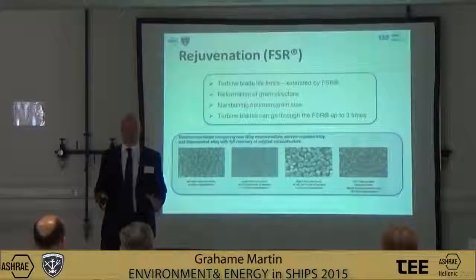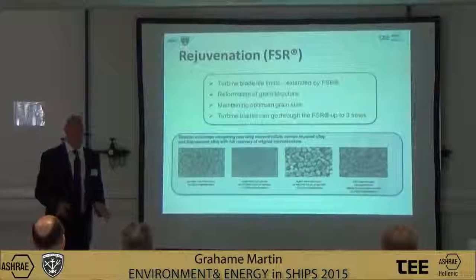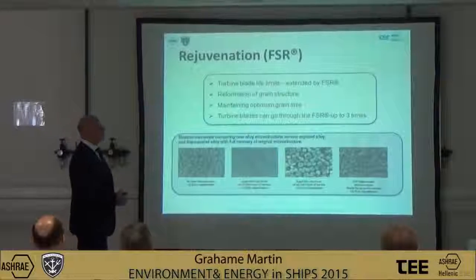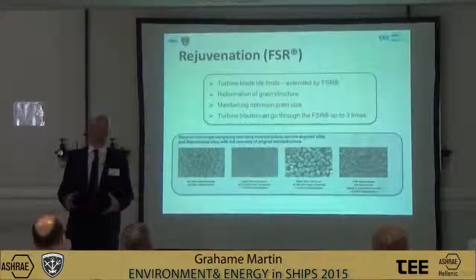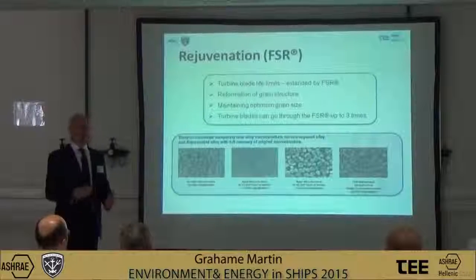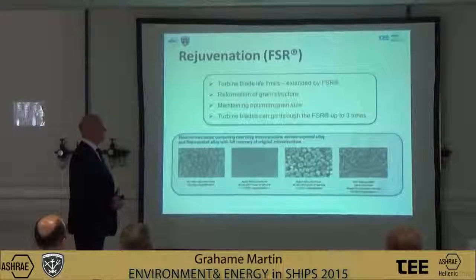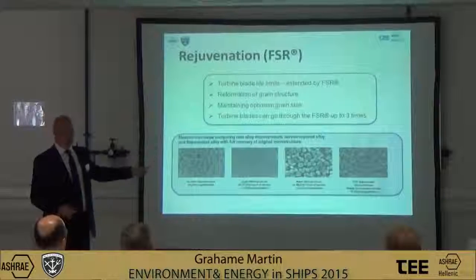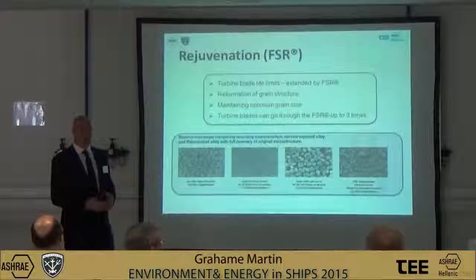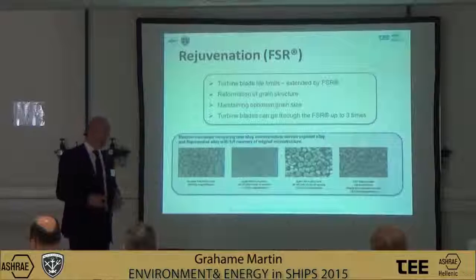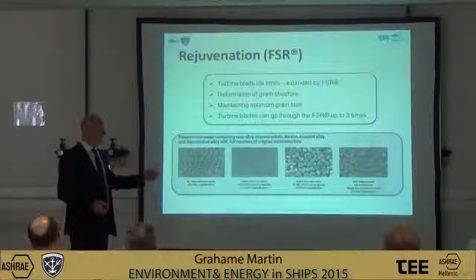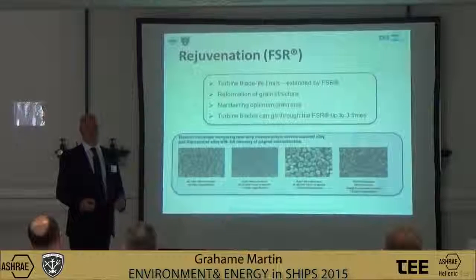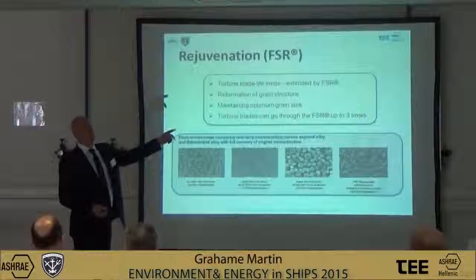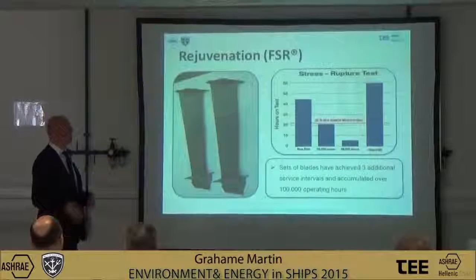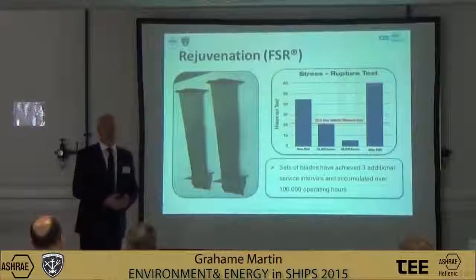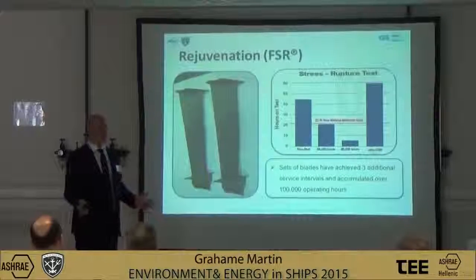This is a huge subject, but what I hope today is to give you an overview of what this actually means, and it's full solution rejuvenation. Basically what it means is that through various heat treatments, we can take turbine blades, put them through the heat treatment, and the effect of the heat treatments is to dissolve the precipitates of the actual blade itself and realign the structure to as good as it was when it was a brand new turbine blade. We can go through this process up to 3 times, and basically it means that you don't have to buy new turbine blades every time you overhaul your gas turbine. We can rejuvenate them for a full service life.